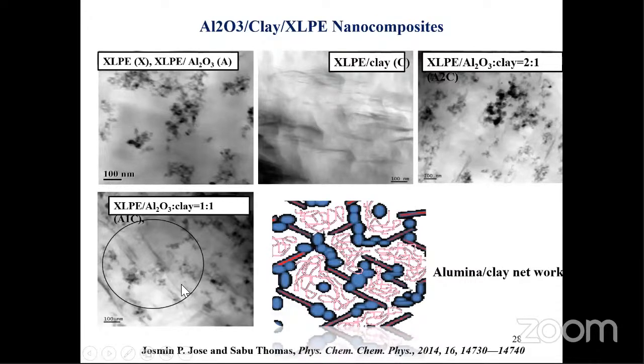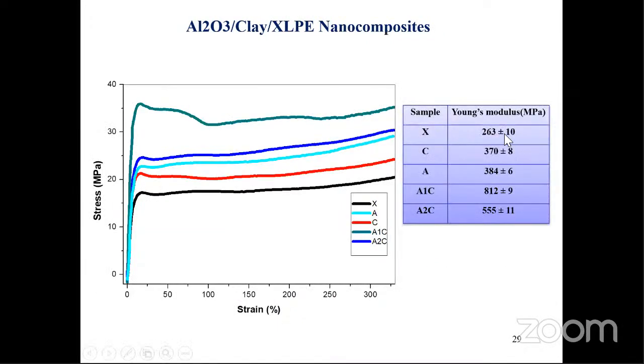You know what we did? We mixed clay and aluminum oxide and put them into XLPE. You know what happened? The clusters have been destroyed and we got a beautiful network formation. You can see this is clay, this is aluminum oxide. Look at this. You get a fantastic self-assembly process when we mix two nanofillers together and put them into the polymer matrix. Look at the mechanics we got.